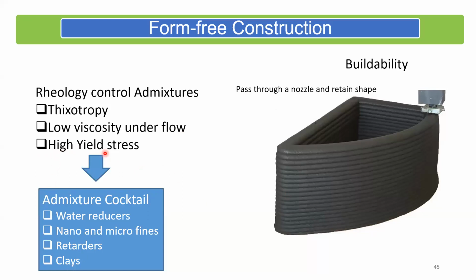The effort required to initiate flow should be high. The effort required to maintain the flow should be low, so low viscosity, and that internal structure in the deposited layer should build up quite quickly so that I can keep adding layers on top of this. And the way we do this, again, goes into a lot of engineering. We have to engineer the rheology of the cement paste. We are using a lot of water reducers now.